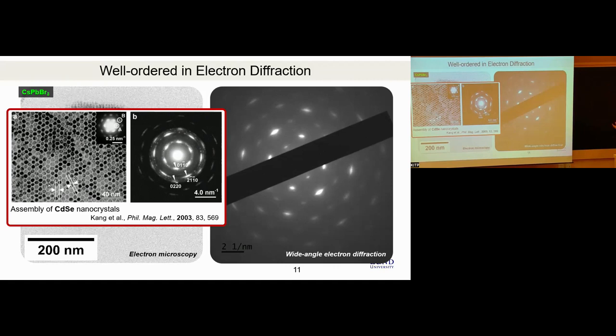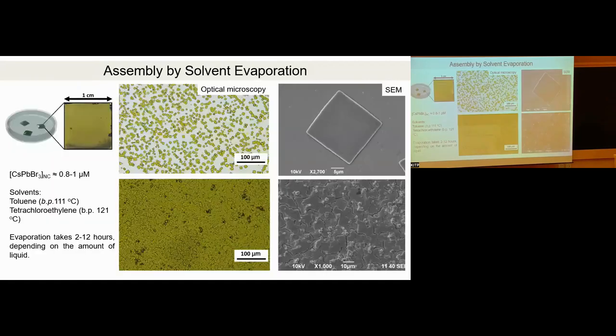So we decided to study it with X-ray diffraction, and in that case we shifted to solvent evaporation, so we can grow superlattices on substrates in this planar fashion, because by the previous method you form aggregates of superlattices and it's not convenient to study. So what we did, we used dispersions of perovskite nanocubes, either in toluene or in tetrachloroethylene. Tetrachloroethylene gives, just empirically, more reproducible results.